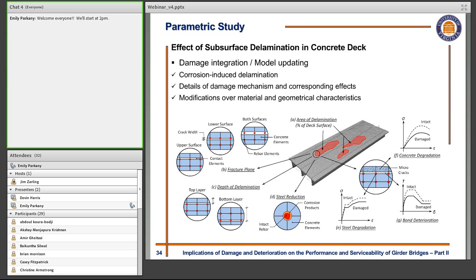In the case of uniform corrosion, we may not need to address the material properties, but in the case of severe corrosion where we have effects of pitting, we also need to modify the material properties because we have degradation of the material properties of the reinforcement. As a result of expansion of these corrosion products around the rebars, we have internal pressure acting on the surrounding concrete. And as a result, we may have macro cracks, especially in the concrete cover area. So this is another detail that we need to include in the models, by reducing the material properties of the concrete in the delaminated area. And the last feature is the bond behavior between the reinforcement and the surrounding concrete, which can vary from perfect bond to ideal debonding, where ideal debonding would be the lower bound of the behavior of the system under the effect of delamination.